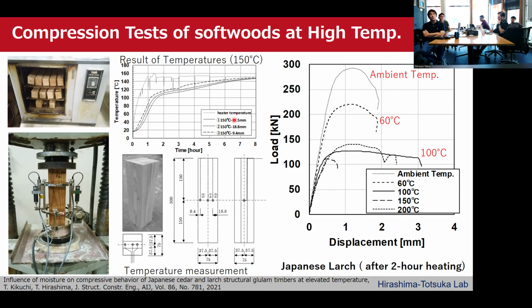This graph shows the relationship between heater temperature and time. And this figure shows load displacement relationships. The temperature shown here is the set temperature of the heater, and the results are shown after 2-hour heating. It can be seen that the compressive strength of the softwood decreases with increasing temperature.